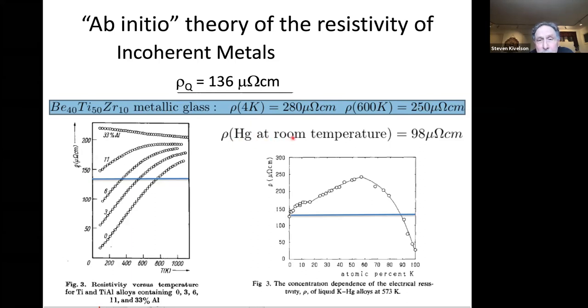Here's mercury, liquid mercury, which of course is not crystalline, at room temperature has a resistivity of 100 micro-ohm centimeters. Here I found that this is for some reason at 573 Kelvin, but they've alloyed potassium and mercury, so this is a liquid alloy. Here's the resistivity of the pure mercury, which in going from 100 Kelvin to 573 Kelvin has gone up from 100 to 130 micro-ohm centimeters. Here's its variation as a function of potassium, until over here where I have pure potassium, it's maybe somewhat outside of my range. But this blue line is, of course, the quantum of resistance.